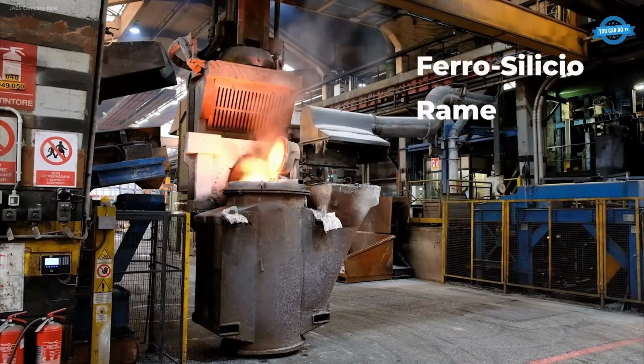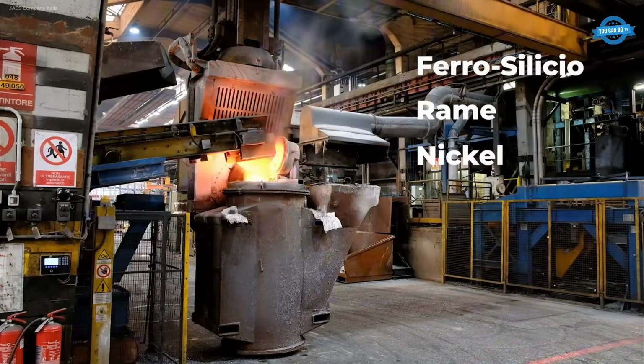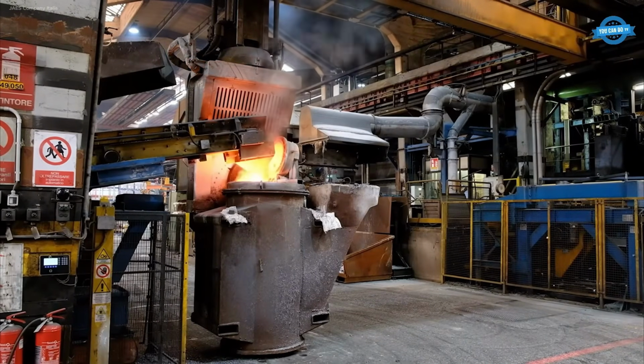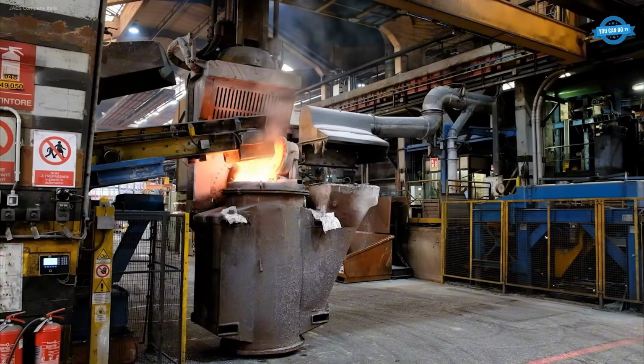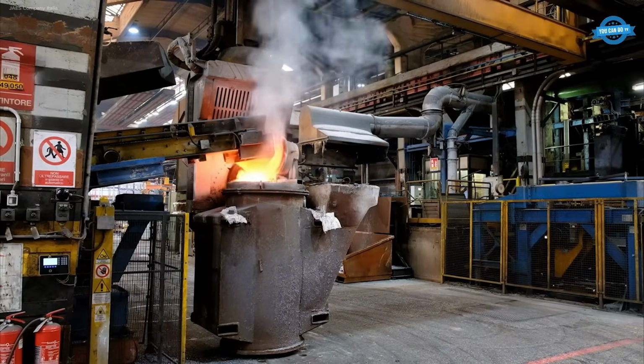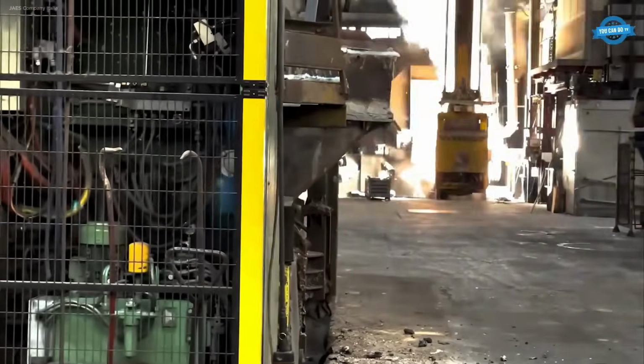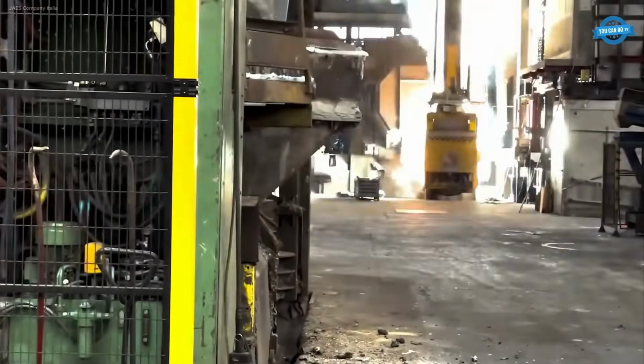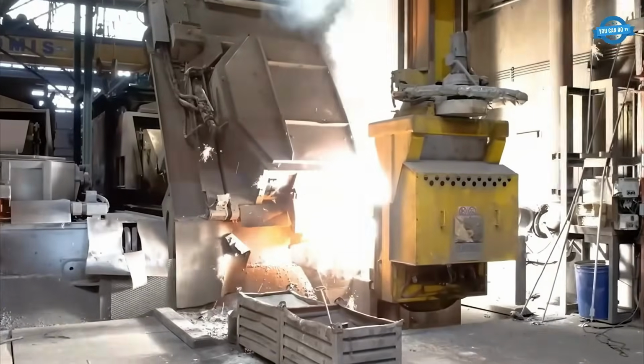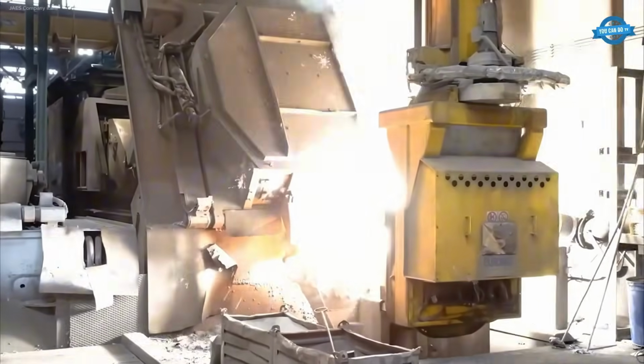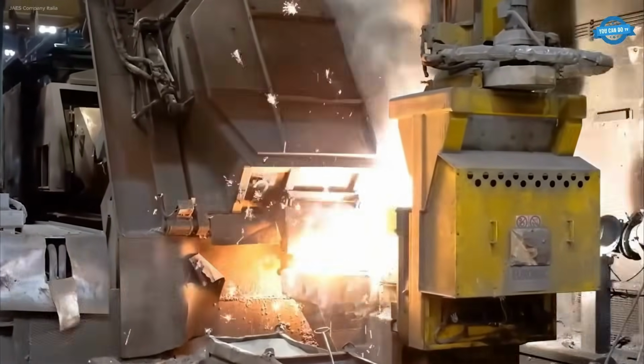Before pouring into molds, a process known as inoculation is performed. Pre-inoculation introduces ferrosilicon alloys that serve as nucleation points for graphite nodules, preventing cementite formation and enhancing structural uniformity. A second post-inoculation is done just before the mold is filled, improving nodule consistency.